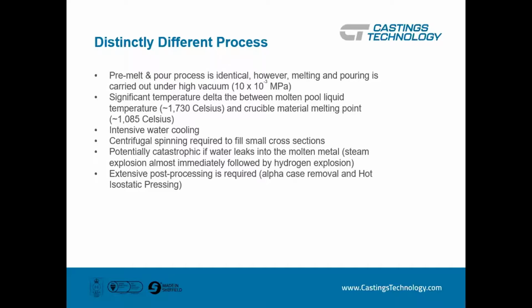And then with titanium, there's some quite intensive or extensive post-processing required. You may know that when titanium solidifies, it goes through a phase change and leaves something called alpha case on the surface. Now, for the younger contingents at work, when I described that under a microscope as looking like crazy paving, none of the younger people understood what that was, but I'm sure you guys will. And it does look very akin to crazy paving. And of course, all of those cracks in that alpha case surface are potential crack propagators. So we have to remove all of that alpha case, and that's where the hydrofluoric comes in.